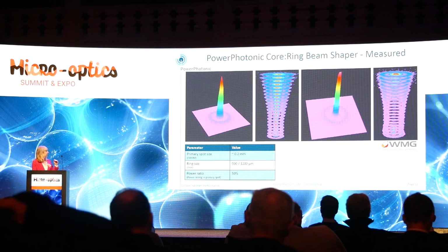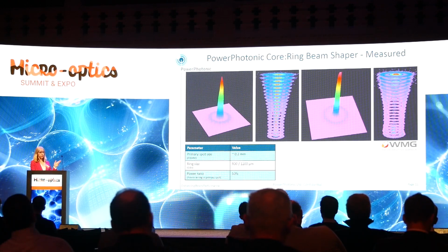As you can see, the core and ring all the way through the caustic. One is a 900 micrometer ring and the other one is a 1200 micrometer ring. But the power ratio for both is 50-50, and looking at it this way it doesn't look like it, but it has exactly the same power ratio around the outside as before.